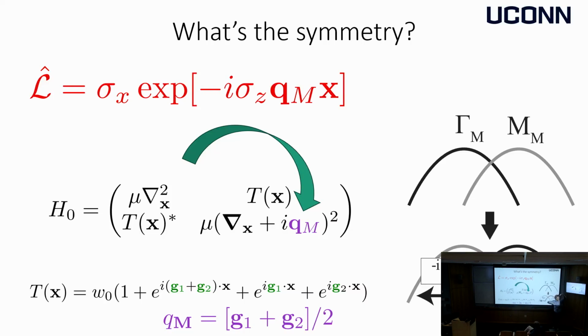Now you can interchange the layers, but the parabolas are not in the right spots in momentum space. So I need to shift them back, and that's what this exponential does. It shifts them back, but in real space, it's modulated. You can actually show that this exponential takes on values of 1 or -1, with sigma z doing nothing, inside each of the moire sites.